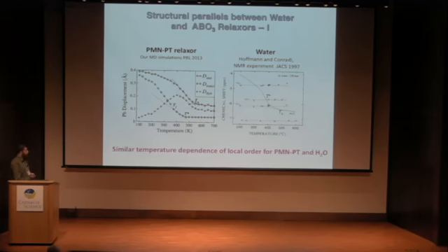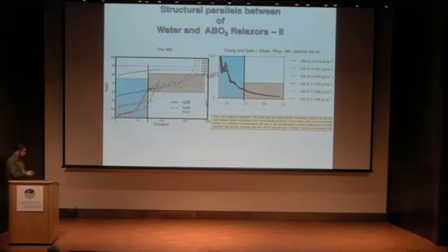So here is again our picture where we see that the change is localized in this 60 angstrom or 6 nanometer region. And this is a paper by Zhang and Gali, also very recent, where they looked at the longitudinal dipole-dipole correlation function using MD simulations. And what they see is that past this 15 angstrom or 1.5 nanometer cutoff, whatever temperature or pressure you use in the simulation, you get exactly the same dipole-dipole correlation function. The change happens over here.